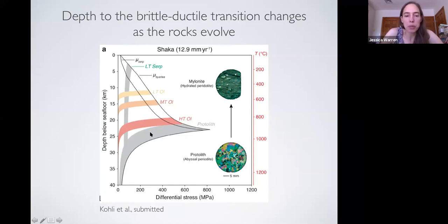And then when we go from the protolith shown in gray here, which is the coarse grain peridotite deforming by dislocation creep or grain boundary sliding, as you move into the high temperature mylonites, we estimate with that grain size reduction that we're moving into a weaker regime, into diffusion creep, and that can accommodate ductile flow at a shallower depth than the coarse grained rock. So we have increasing shallowing on the fault with these changes in the rheology of the system due to the grain size reduction of the olivine.